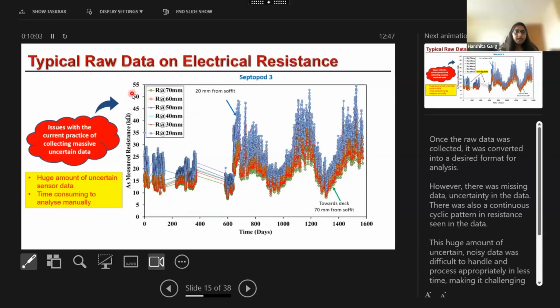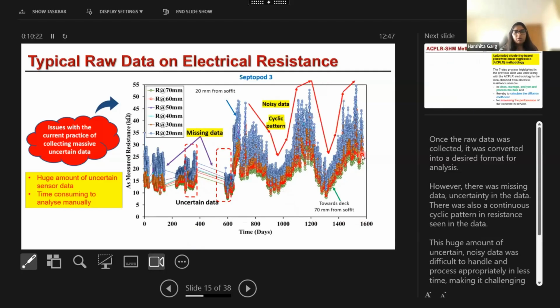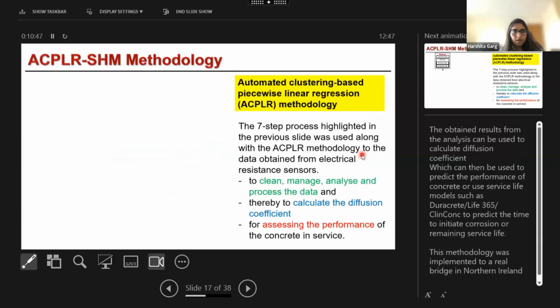So this is the original data that we got. This is the raw typical data of electrical resistance. And here you can see that there is missing data, the single lines. Here the data is going up and down. There's uncertainty in the data. There are cyclic patterns. The data in itself is huge, and it is difficult to manually analyze and also time consuming. Therefore, all this led to the use of some algorithms which could help us in processing it easily and efficiently.